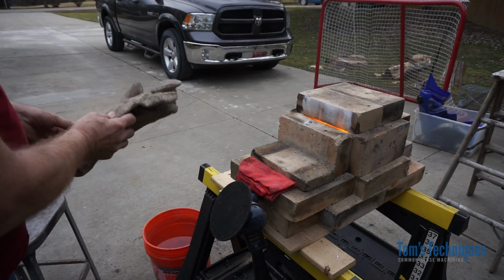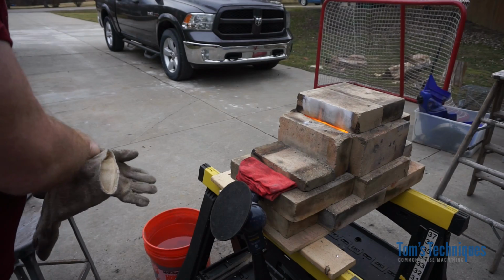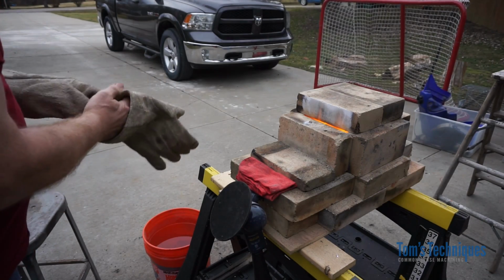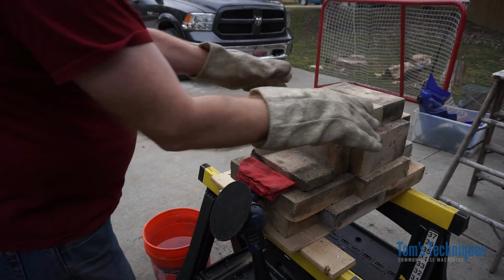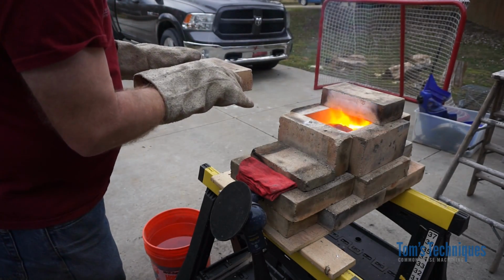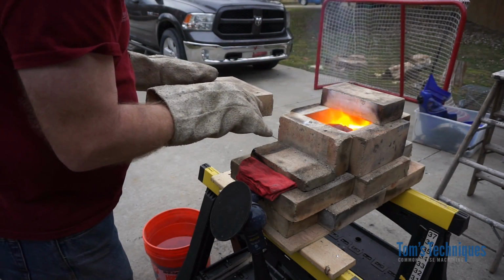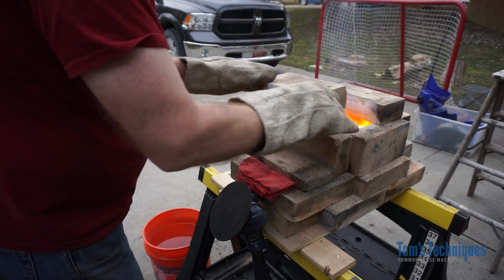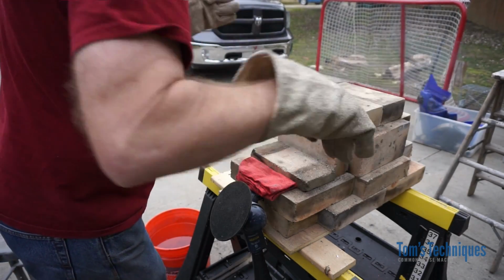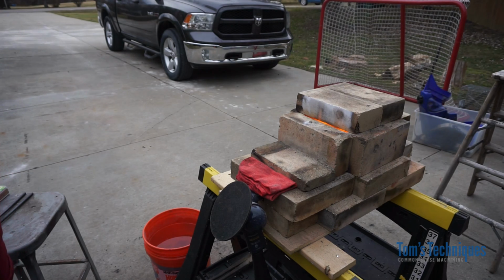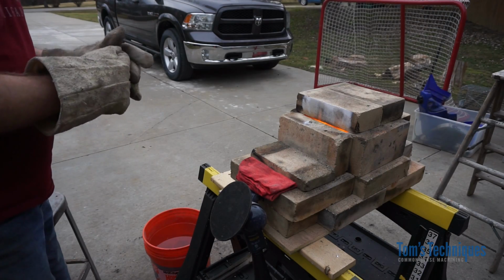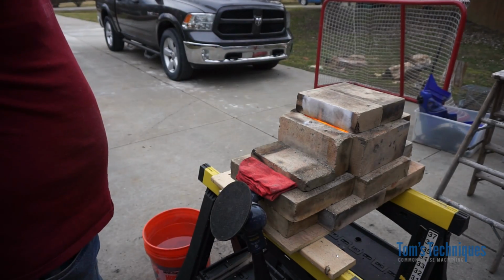Okay, I think we're good to go. I think we've got a pretty good case on this thing. It's been like that for about an hour now. That's probably about 1500 degrees or so. And 1500 degrees in an hour should give us at least 10 thousandths of case on the part. Obviously, there's no hurry in this. The longer you go, the deeper the case will get.